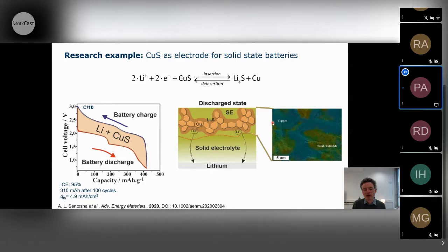This is a cross-section of our cathode after discharge. You can see you really have a copper network, and the particles are very large, several micrometers in size. For this reason, this reaction is called a displacement reaction. So it is a conversion reaction, but a special one, and the correct term for it is the so-called displacement reaction. For sodium, this doesn't work as well, so that's why I don't show the results, but so far we were not able to obtain competitive results for sodium in this case.